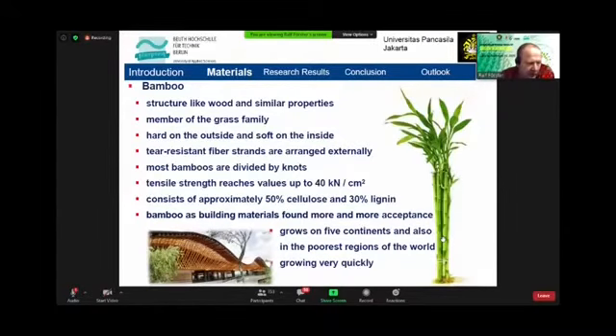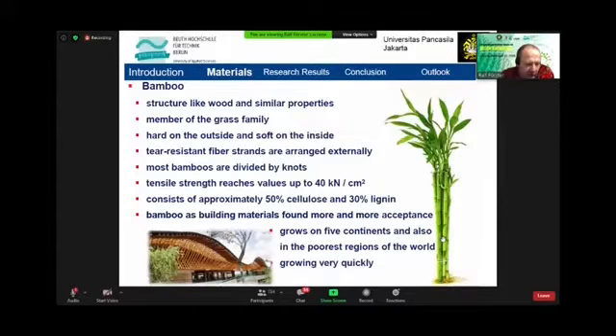Yes, all of you know bamboo much better than the Europeans. The structure of bamboo is similar to wood, and the basic properties are also similar, but bamboo is a member of the grass family. It's not a wood, it's a grass. There is a hard outside and a soft inside. It has very tear-resistant fiber strands, and most bamboos are divided by knots. The tensile strength of the bamboo grass reaches values up to 40 kilonewton per square centimeter. The main content of bamboo is cellulose and lignin. This is also similar to wood.